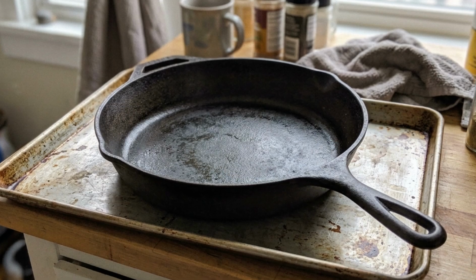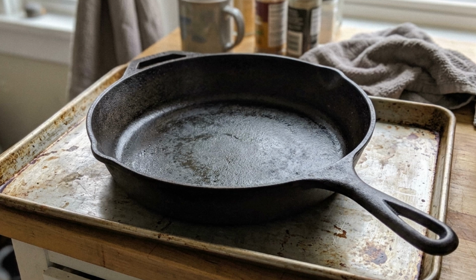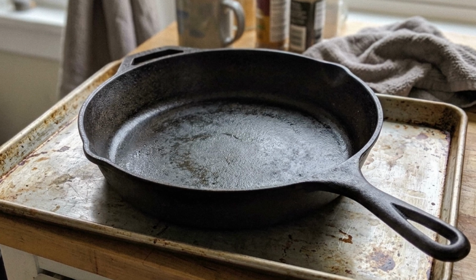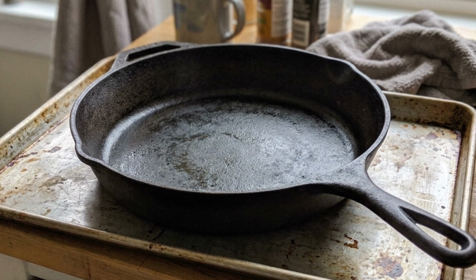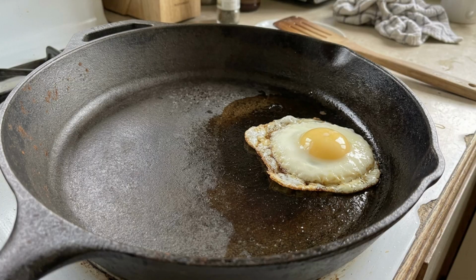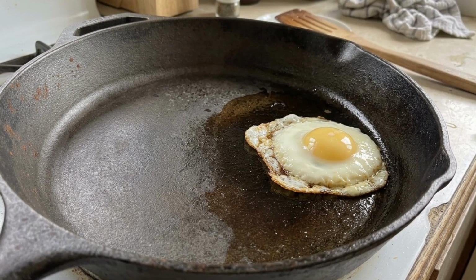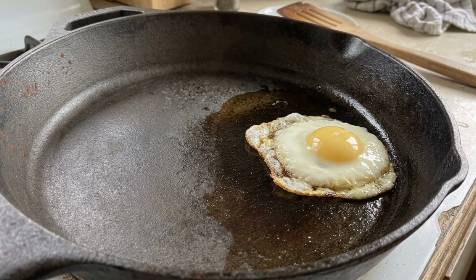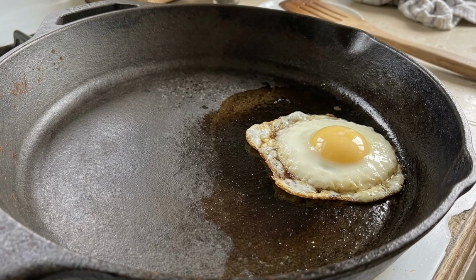Let it cool briefly. Then coat the entire pan with avocado oil. Wipe the excess until almost nothing appears to remain. Place a baking sheet below and bake the skillet upside down at 450 degrees for 30 minutes. Cool it before each new coat and repeat the process 3 to 5 times. I did 5 on this restoration. Then fry the egg and see what you built.